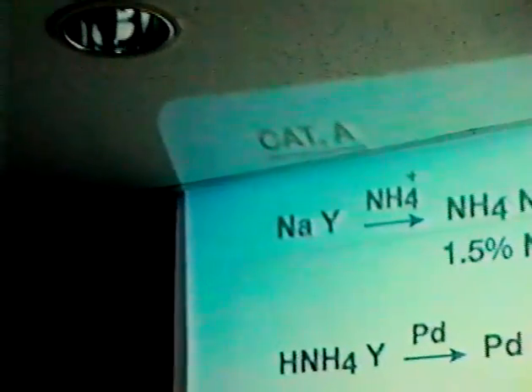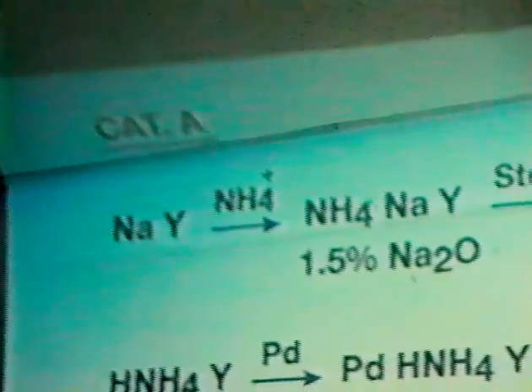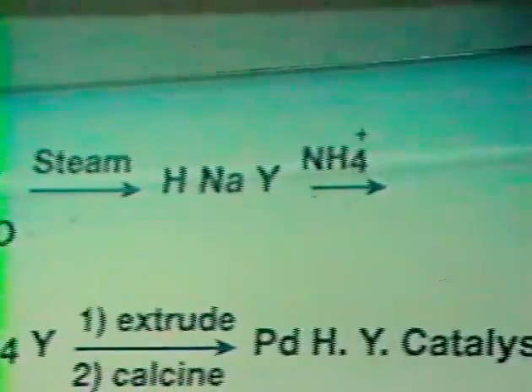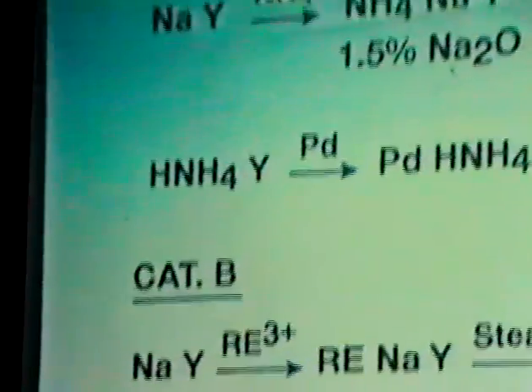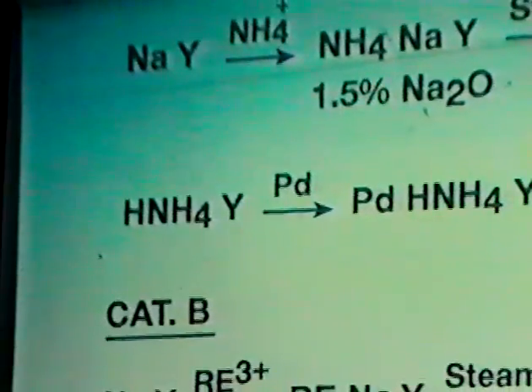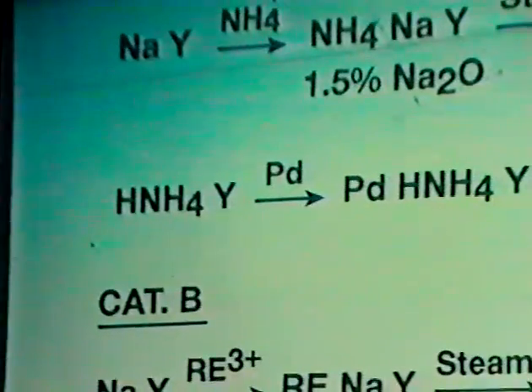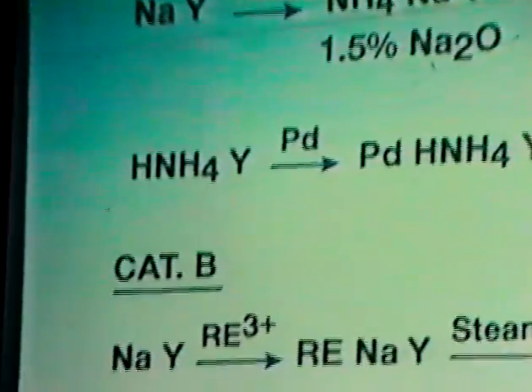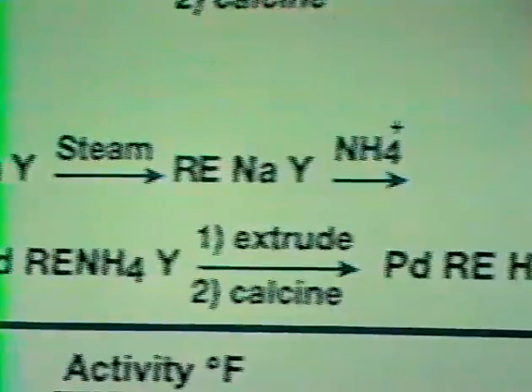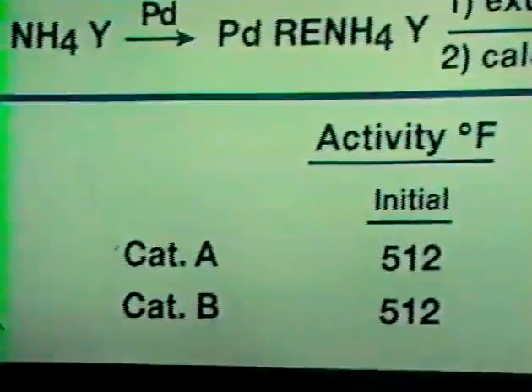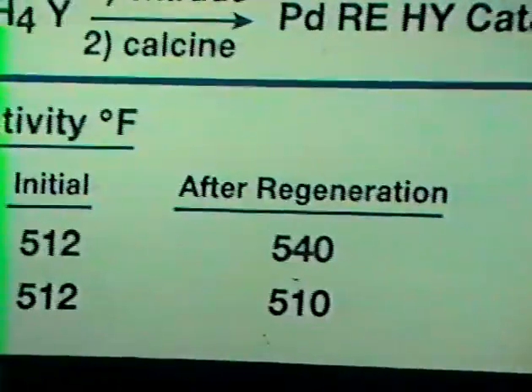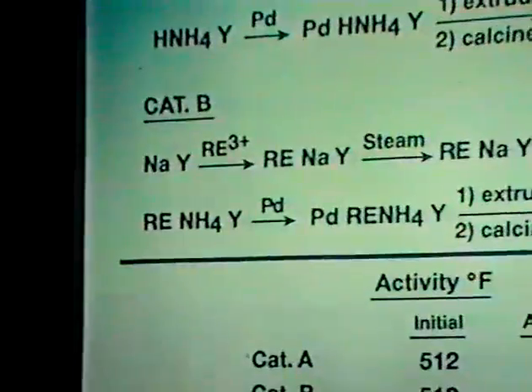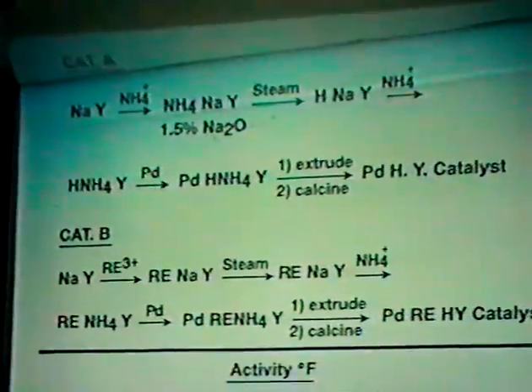Another problem we run into with this type of catalyst is that if we make the catalyst as we described initially, we evaluate it in a test reactor and get a temperature of roughly 500 degrees, 510 degrees for a given conversion. We then take the catalyst, burn off the carbon, regenerate it, and it deactivates to 540 degrees, which loses more than half of its activity. However, if we put rare earths into this catalyst at an early stage in synthesis, we get the same initial activity, and its activity after regeneration remains the same.